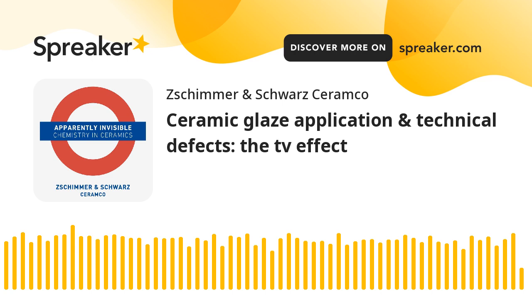So I go back to our TV screen problem with another question, the last question we would say. How can we prevent the movement or migration of the glaze, avoiding the TV effect? Well, two are the most important options to better manage the problem. The first consists in increasing the glaze draining times on the tile support by means of proper chemicals. This action is able to stop the migration process of the glaze, forcing the glaze to remain in its original position.